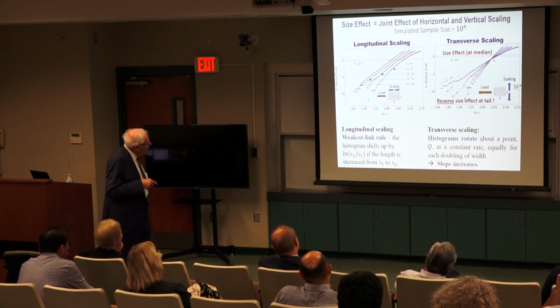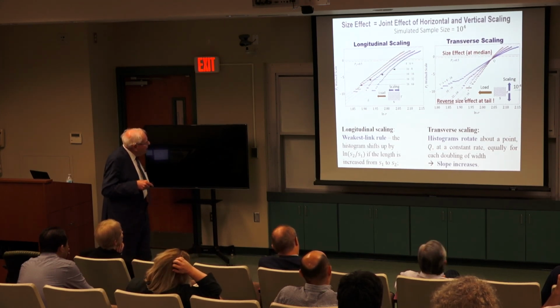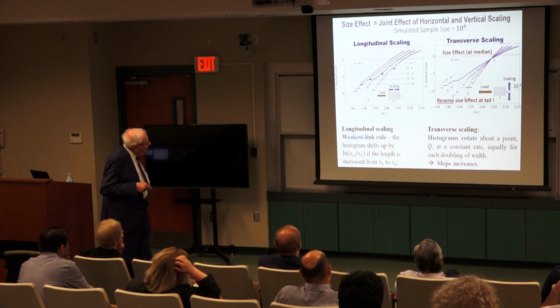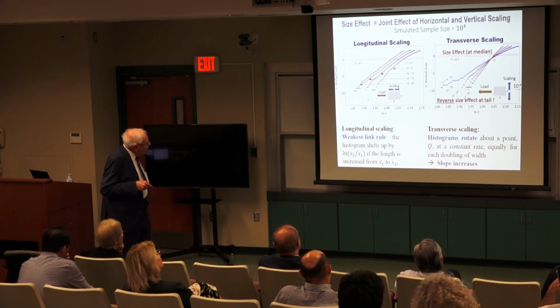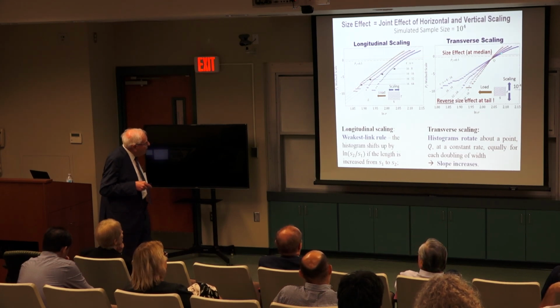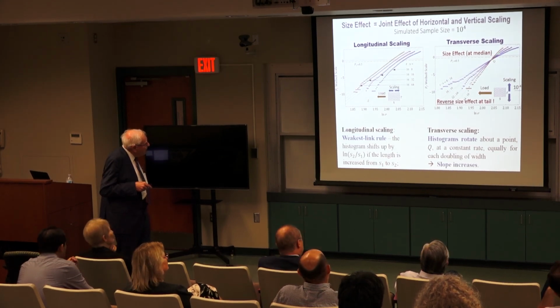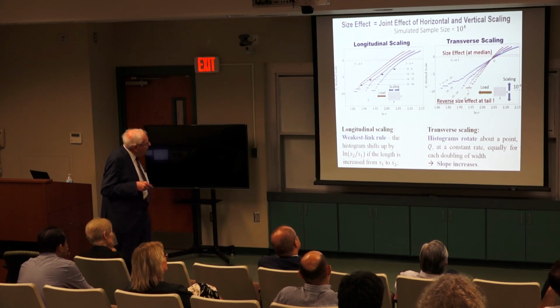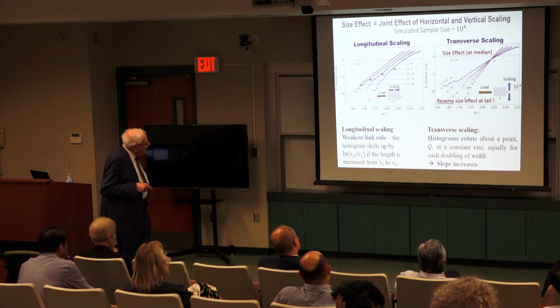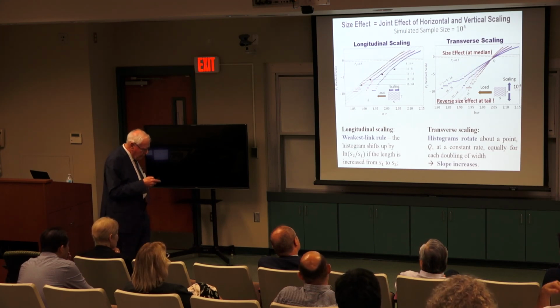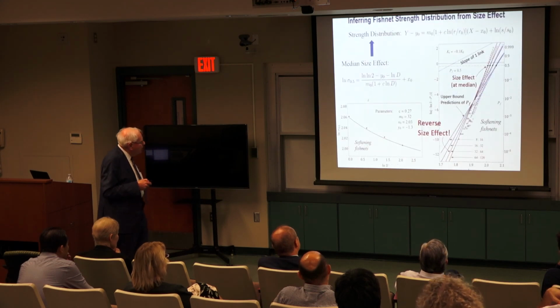And then actually we can put into simple formulas. And if we do transverse scaling, interestingly, all the distributions rotate about 1 point. And I can actually show that it has to be about 1 point. So here you have positive size effects. Structure is bigger, it is weaker. But if you give the transverse scaling, the opposite happens. Now which one wins? You must put these two together. And if you put them together, you see this picture.